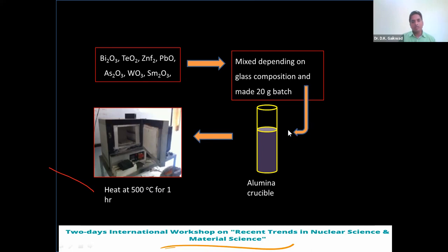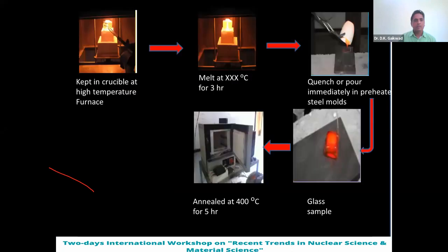We transfer this batch to an alumina crucible, and this alumina crucible is transferred to a furnace for oxidation. We oxidize the mixture for 1 hour, or depending on the composition of the glass. Then the oxidized mixture is placed in a furnace at high temperature to melt, and we shake the mixture frequently to avoid bubbles or inhomogeneity in the melt. Then the molten liquid is quenched and transferred to a mold, and in the mold we get the glass.